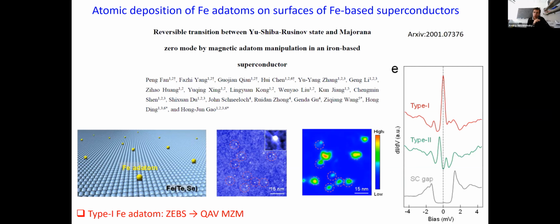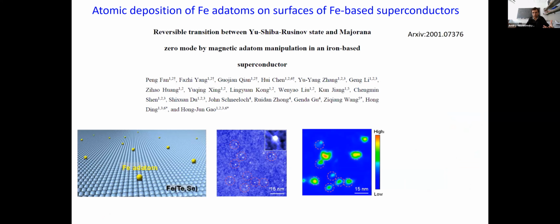I see. And sorry, if I understood correctly, please correct me if I'm wrong. I'm trying to get a two-sentence summary of what you said, which was a lot of material. In the first part of the talk, you argued that there are non-abelian vortices, the ones that give you topologically non-trivial zero-bound Majorana states. In the first part of the talk, they come from the underlying Z2 invariant of the topology of the bands, correct? Yeah. The second part of the talk, you said, well, forget about the topology. Even if somebody gives you a plain vanilla superconductor like lithium-iron arsenic, if you imagine putting add atoms with strong enough spin-orbit coupling, you could have either Yu-Shiba-Rusinov states, or you could have these other non-abelian states. And which one wins depends on energetics. And it's possible that even in the same sample, you might have both. Is that a fair representation?